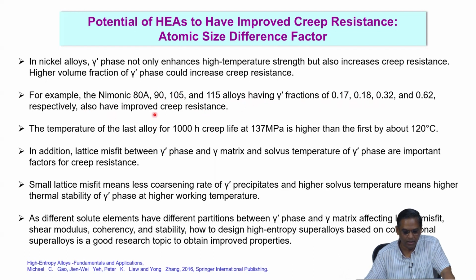The temperature of the Nimonic 115 alloy, okay, for 1000-hour creep life at 137 MPa, is higher than the first by about 120 degrees. That means Nimonic 115 alloy has a better creep resistance than Nimonic 80A. So that is the idea.